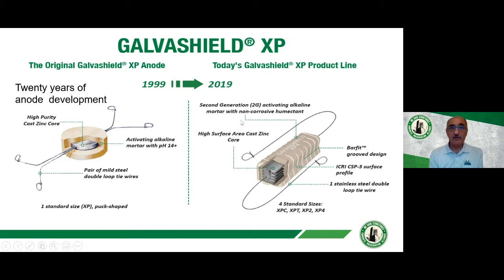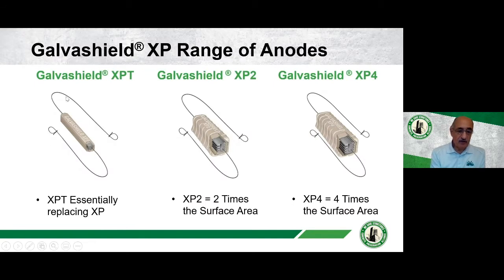And for cases where there may be drying of the concrete and the anodes are at risk of drying, particularly when they're being placed too close to the surface, we developed what we call a 2G generation, where we've included a non-corrosive humectant to maintain a high moisture level in the anode itself. This is what actually replaced the XP anode, the prototype that I've been talking about most of the time. So the XPT, as it's now called, has replaced the XP.